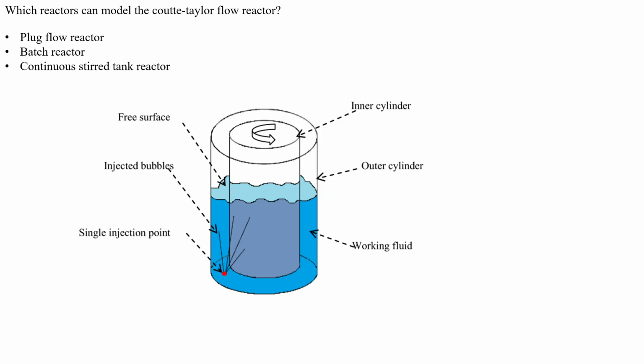But the main problem because of this is that coagulation can occur. Why? Because since the annular space is there, if the polymerization mixture viscosity increases a lot, your viscous forces will overpower the rotational forces, and sometimes because of that, the polymer might settle down. So that is one of the problems which can be faced in this case. Remember these things because these are the small things which can be asked as questions in the exam.